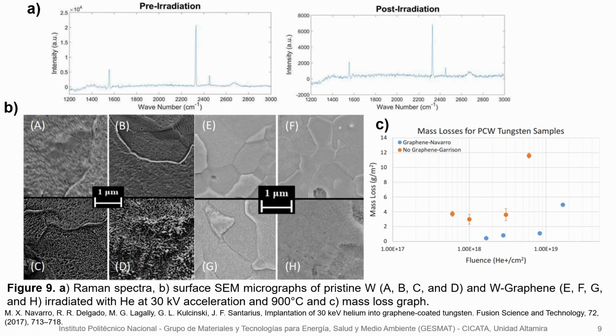On the other hand, graphene has been studied as a radiation barrier to protect tungsten material from irradiation. Tungsten samples were irradiated with helium at 30 kilovolts of acceleration and 900 Celsius. In the micrographs from A to D, we can see that with the increase of helium fluence, the surface is damaged, giving at the highest fluence a fuzzy surface. E to H micrographs are tungsten samples coated with graphene obtained by CVD.